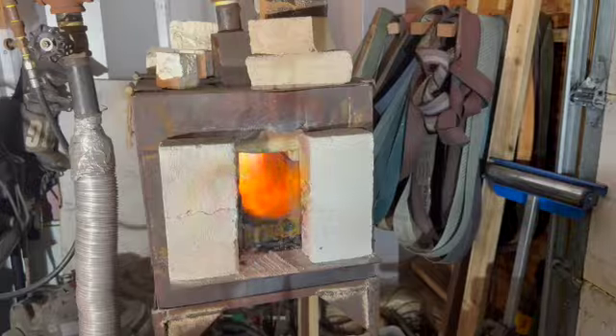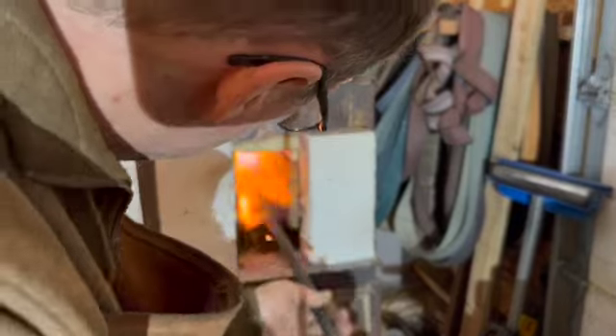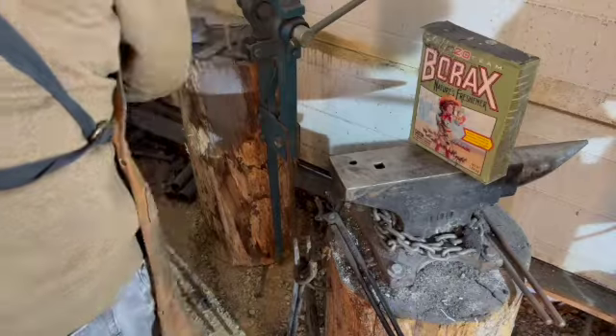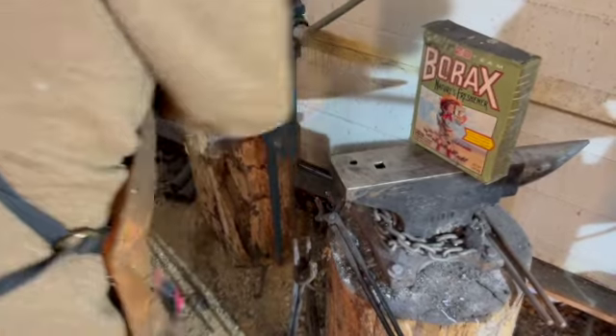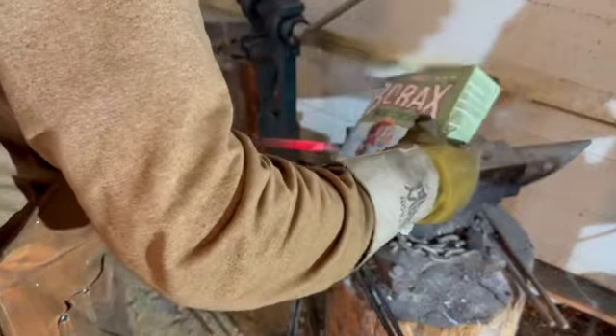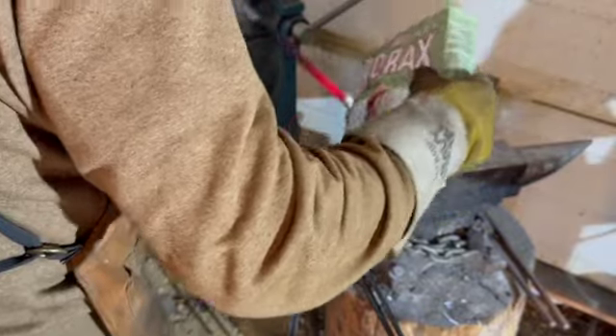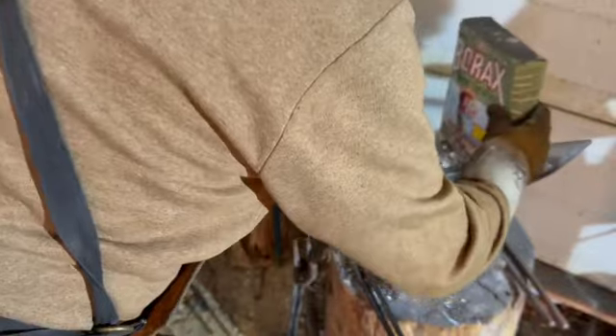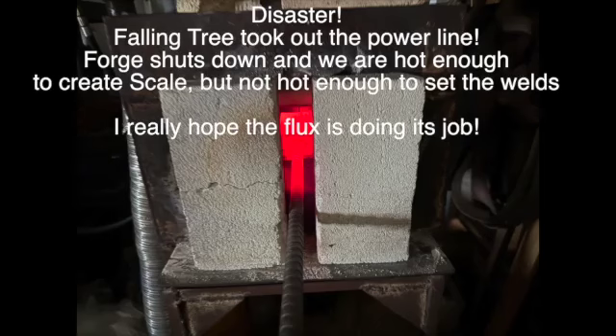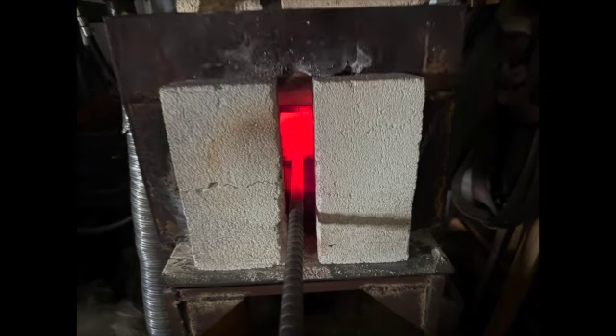I'm going to throw it in the forge, but we ended up with a problem today. There is a windstorm outside with winds reaching 60-70 miles per hour. And what happens is the power goes out as I'm heating up the billet. I was really worried that with the billet heated up to about 1200 degrees and then the power going out, my ribbon burner forge has to shut down because there's no air blowing. I didn't know if I just ruined the billet or not.